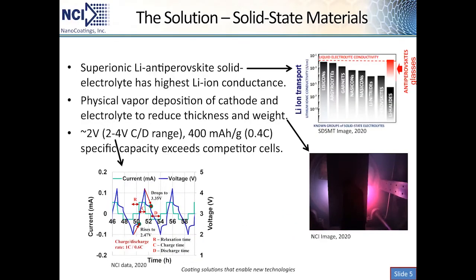Our solution to the problem of flammable and volatile lithium-ion batteries is to use solid-state materials. We have selected a superionic lithium antiperovskite material as our solid electrolyte, which has the highest lithium-ion conductance of candidate solids shown in the upper right figure, including garnets and sodium-containing electrolytes, and lithium ion transport that is consistent with or possibly exceeding liquid electrolytes. To do this, we're using a novel radio frequency powered physical vapor deposition method of the electrolyte, as well as a cathode material using state-of-the-art lithium iron phosphate material to reduce the thickness and weight of